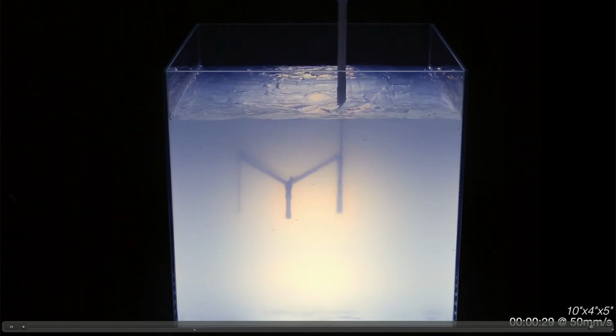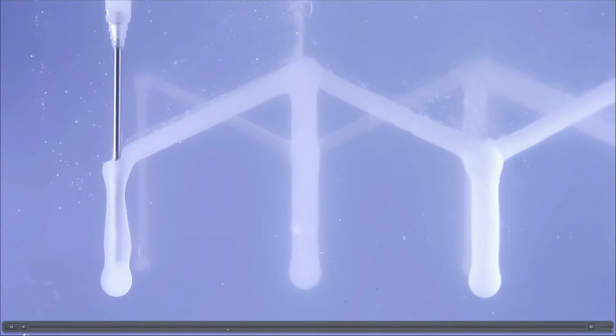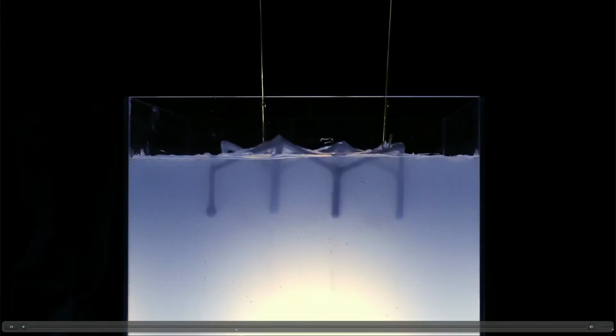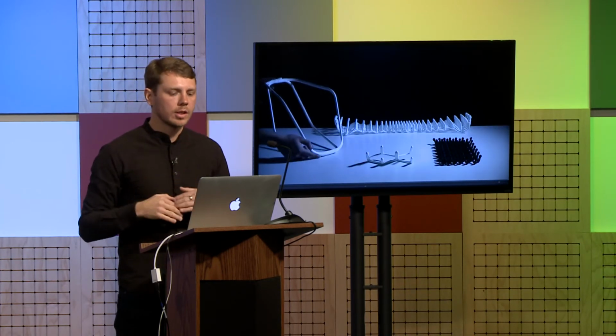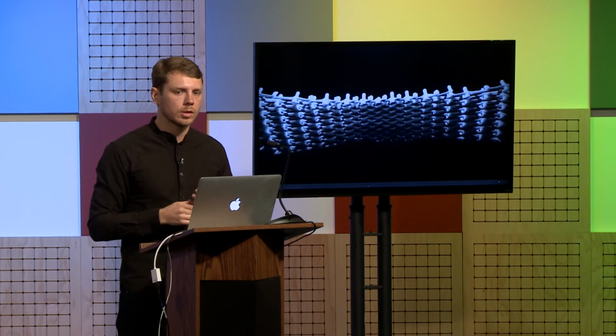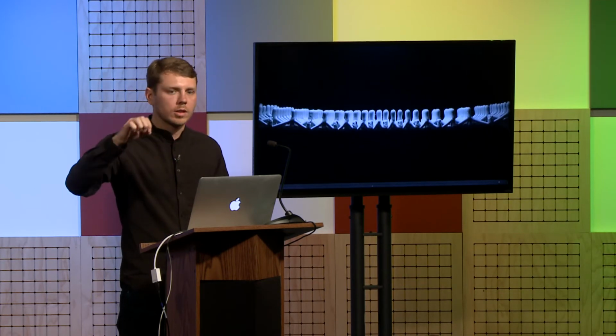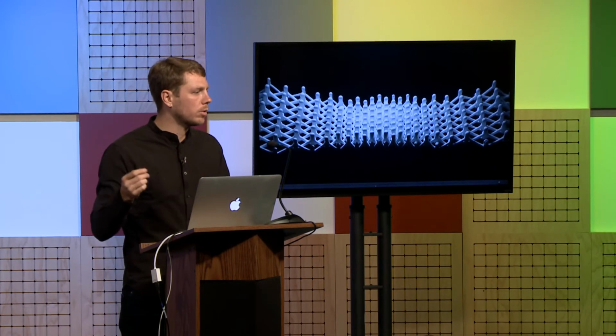So this is much, much faster because normally in 3D printing, you have to go layer by layer. And in our case, there is no layers. You just draw in 3D. But you also don't have to print support materials. Like normally in 3D printing, if you wanted to print that shape, you'd have to print all the support material so it doesn't collapse with gravity. In our case, the gel is the support material. And then we don't have to wait for it to cure. Like in FDM printing or SLS printing, you have to cure the material at every single step. We just draw the whole thing and then it cures all as one.